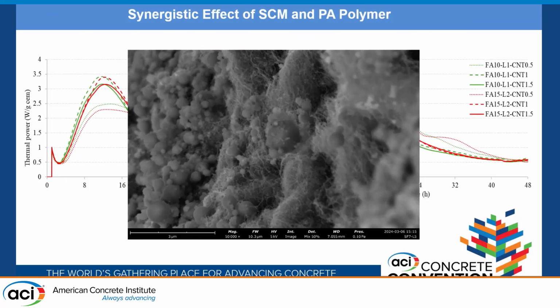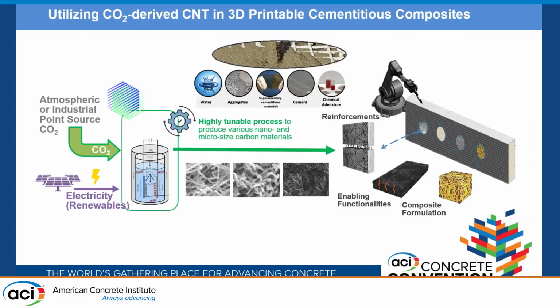So again, these are some examples with a high amount of CNTs and a high dose of silica fume. You can still see the silica fume is acting as a carrier medium in this case to try to disperse that. So this is a preliminary study that we did. We were trying to make a functional cementitious system with a higher dosage of CNT and use that for 3D printing. What we did with this study is a little bit different from the previous.